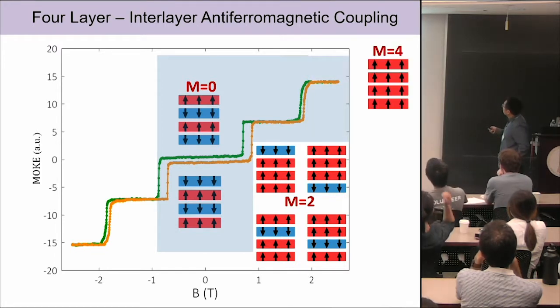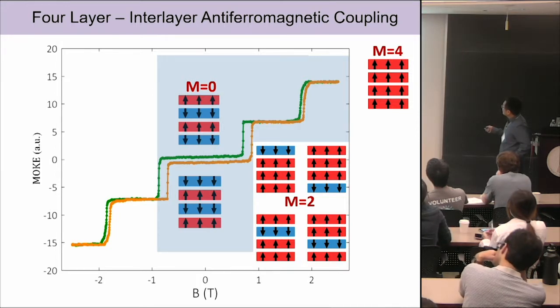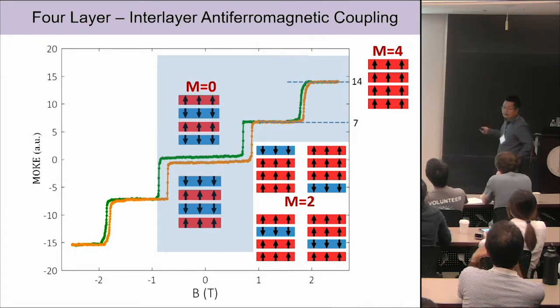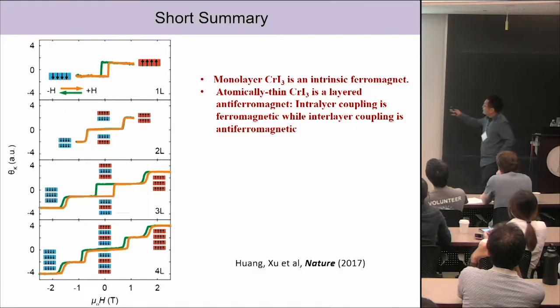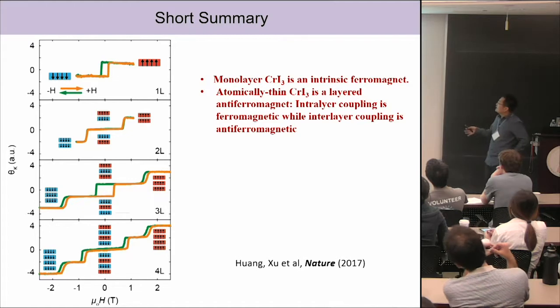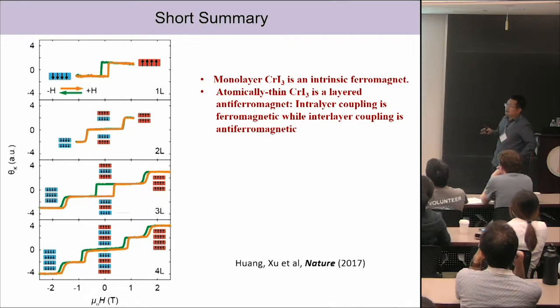And the last one is when you apply the field and you get net magnetization 4. Then the signal from this state to the intermediate state should be 2 to 1. That's about what we see. The top is 14, the middle level is 7. So everything works well. The short summary is that monolayer chromium triiodide is an intrinsic ferromagnet, and for atomically thin chromium triiodide, the interlayer coupling is anti-ferromagnetic.